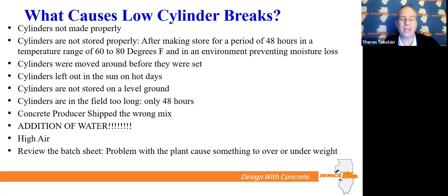Cylinders in the field too long. They can only stay 48 hours, right? We see sometimes people make cylinders on Friday and don't pick them up till Tuesday. That's way too long. Sometimes it's a concrete producer's fault. Maybe you shipped the wrong mix, or added water. We talked about water cement ratio. The more water you add, you break that water cement ratio, and you're going to cause low breaks. High air, right? The concrete's designed to be between 5 and 8%. If you have 10, 11% air in your concrete, your strength's going to go way down, so you'd get bad cylinder breaks.